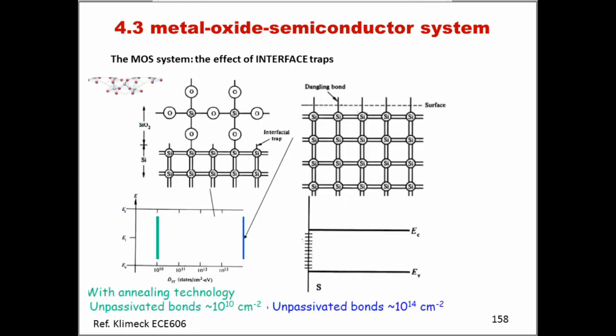Now, let us have a look at interface traps. Interface traps arise because of the mismatch between the lattice of the insulator and the lattice of the semiconductor, if we're talking of the oxide-semiconductor interface. This is highlighted here by showing the lattice of the SiO2 insulator and the lattice of the silicon semiconductor. As you can see, there are some silicon bonds that are effectively dangling. They don't bond to any other atom of the insulator lattice, and so this creates an interfacial trap.